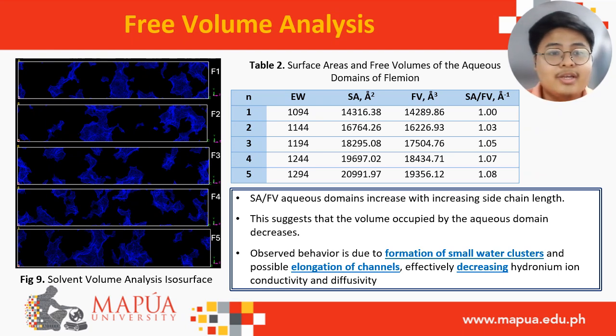Here, in the free volume analysis, we will be able to understand what the aqueous and polymer domains are. In figure 9, this is the solvent volume isosurfaces, wherein the blue figures represent the aqueous domain. Here in table 2, we have the surface area, free volume, as well as its ratio. And we can see that the surface area to free volume ratio of the aqueous domains increases with increasing side chain length. This suggests that the volume occupied by the aqueous domain decreases. The observed behavior is due to the formation of small water clusters and possible elongation of channels, effectively decreasing hydronium ion conductivity as well as diffusivity.